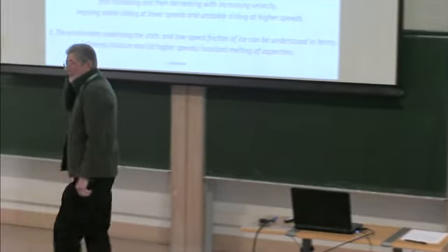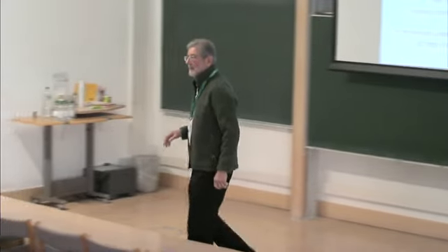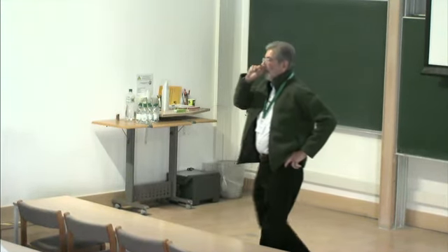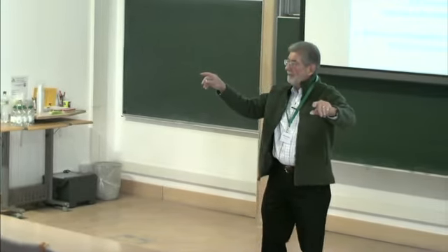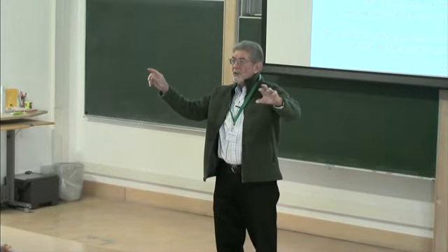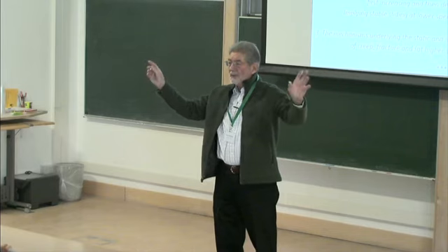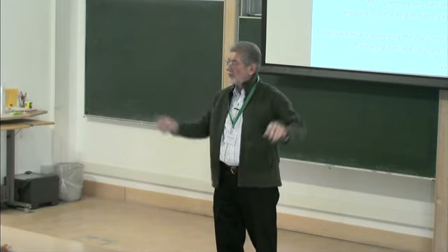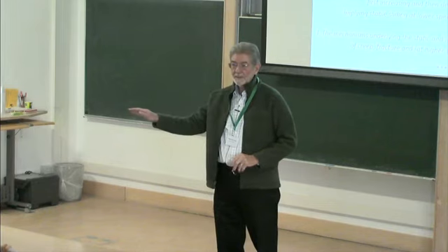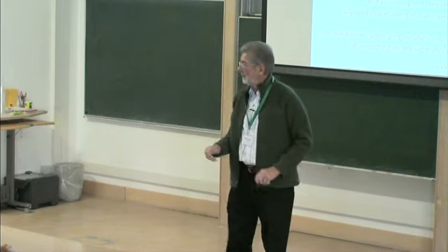Can I just follow on from that point? So, yeah, that's right. But the tensile strength depends upon the porosity, and the porosity depends upon the internal salinity. Oh, indeed. Tensile strength, different story altogether. Yeah, no friction in tensile strength. No, take friction out of the story. It's only fracture toughness and defect size. No friction. May I ask one more question?